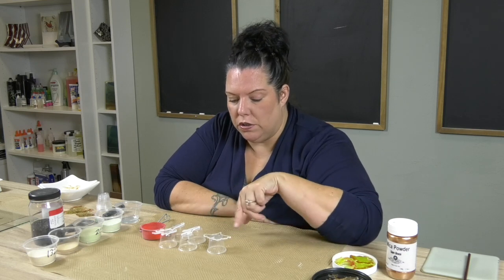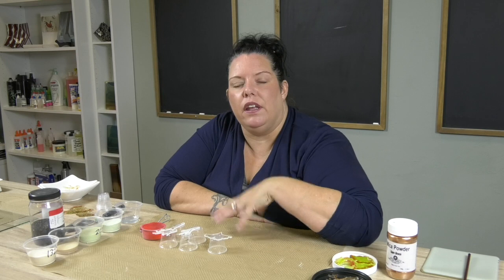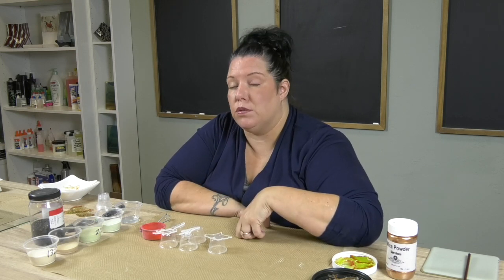So the first thing we need to do is prep these pieces with powder. We're going to use opal powder. Here's the thing with powders. Whatever you put down seems like a lot, but it's not enough, okay? So people hear this and start mounding up the powder really thick, and then they've got uneven powder and what's called flashing, and it especially happens with the transparent powders.